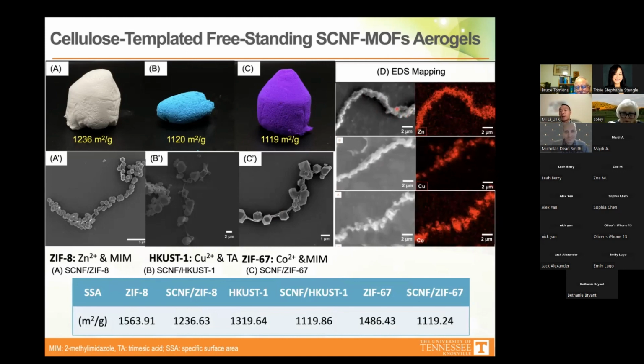So for example, on the top right here is zinc, shown in red. Basically you can tell the zinc metal ions distribute along the fiber, and this is for the copper, and this for the cobalt. So the information right here tells you that the metal ions are well dispersed along these fibers. And the table below shows you the surface area.